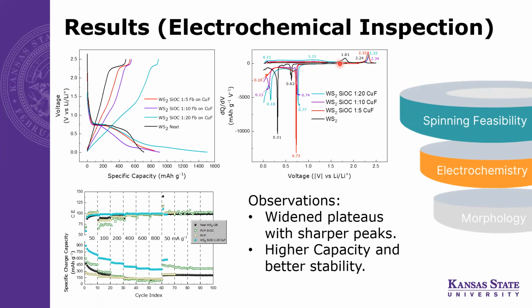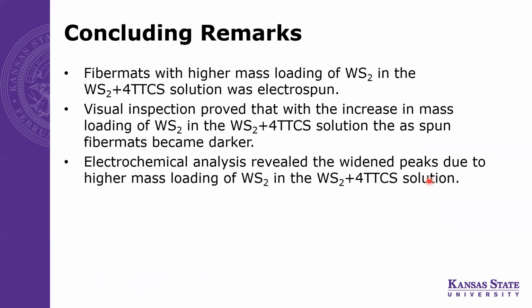Finally, this composite electrode was tested as lithium-ion battery material, which showed a capacity of 600 milliampere hour per gram, which is more than 1.5 times that of the traditional anode material, graphite, that is used in current lithium-ion batteries. So finally, we can say that the reinforcement actually improved electrochemical properties, and the electrochemical signature can capture the result.